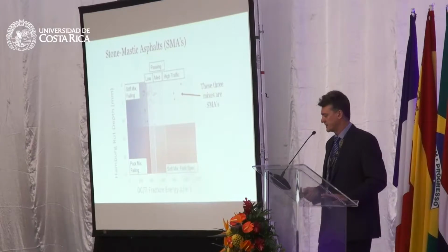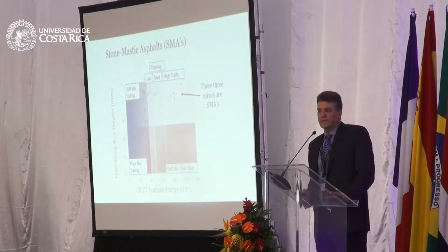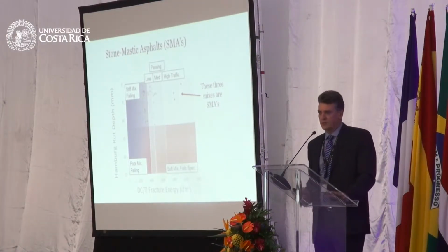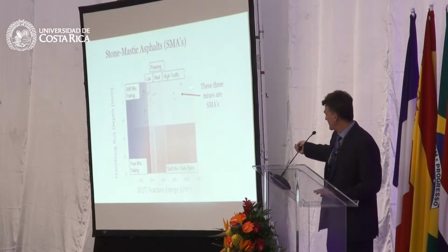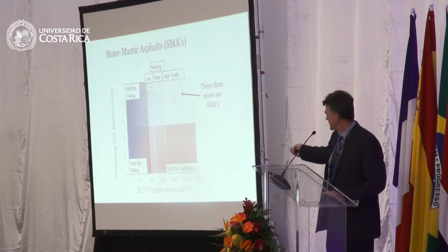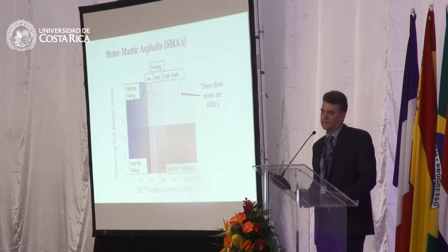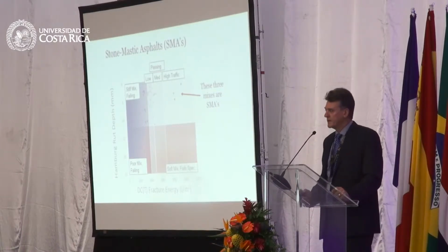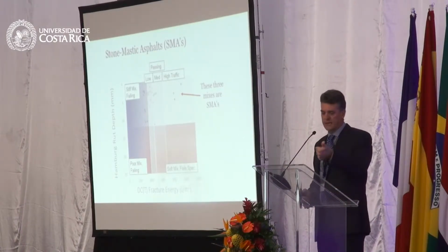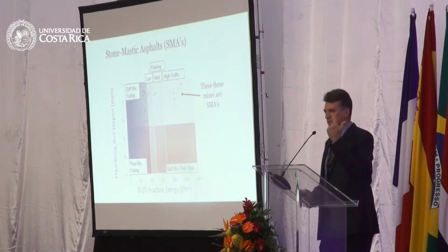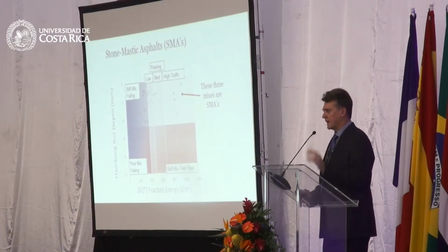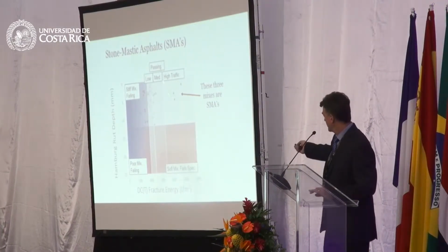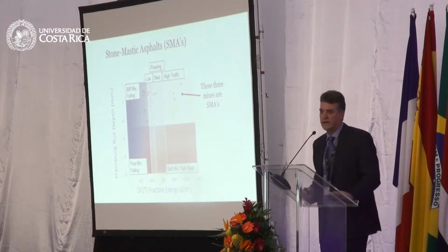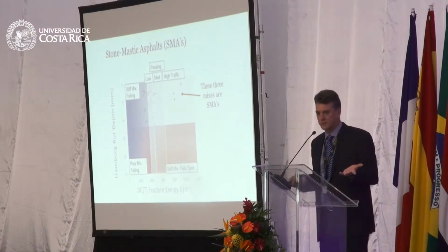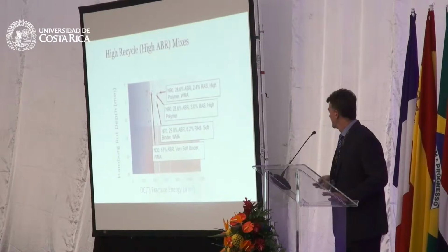When we develop very high performance mixtures like stone mastic asphalt, they perform drastically different than dense graded mixtures with lower amounts of polymer modified binder. So when we invest in a stronger rock with a better gradation, polymer modified binder, thick films of asphalt, we truly do get to a very high performing mix. And we know that these mixtures work very well in the field.